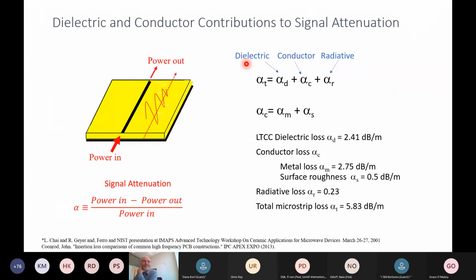So just doing an accounting exercise, and again, this was done a while back, we look at the different contributions to this attenuation. So power in, power out, and the attenuation is really related to what fraction of the microwave power makes it out. We could actually total up the contributions in terms of a dielectric contribution, a conductor contribution, and a radiative contribution. The conductor has basically been broken out into two contributions, the metal and the surface losses, surface roughness, because we know there's a skin depth associated with this as well. As we push to higher frequencies, this will become more important as well.